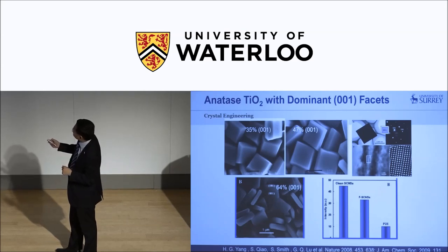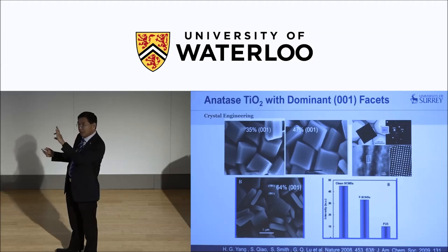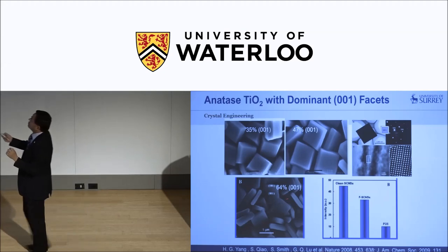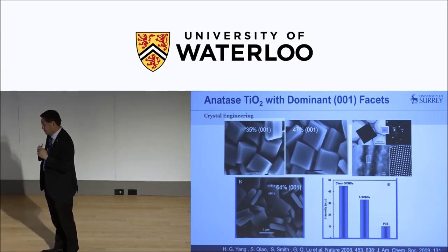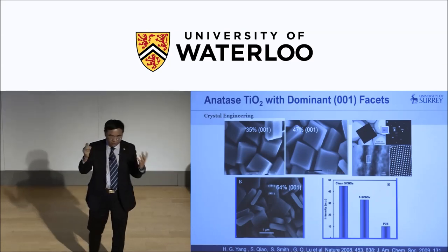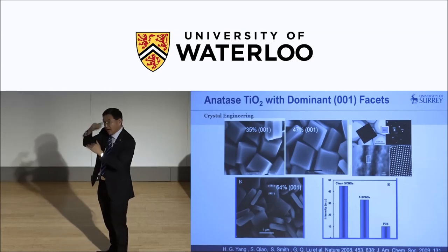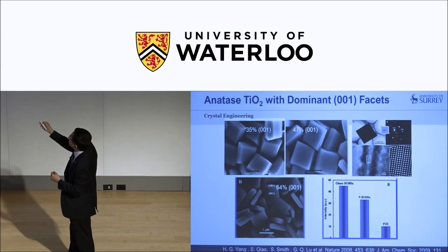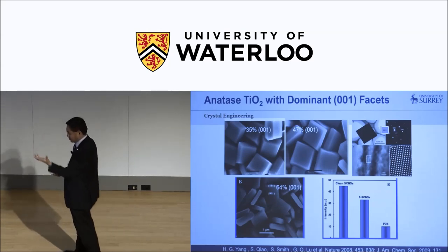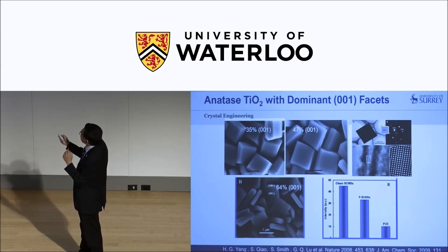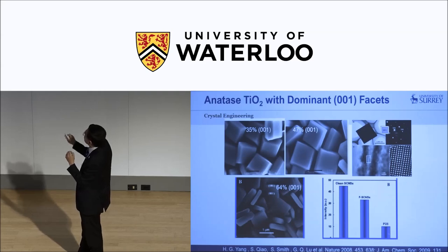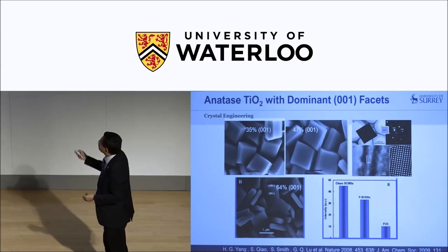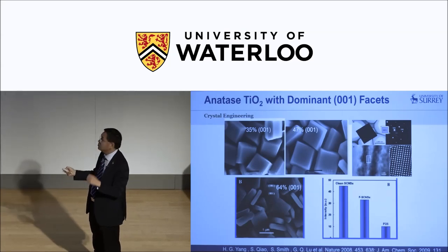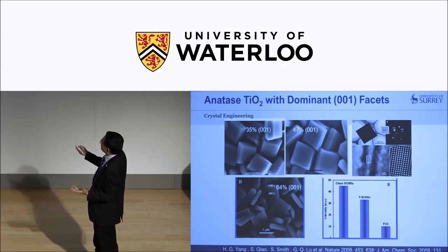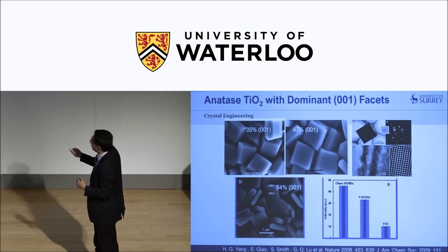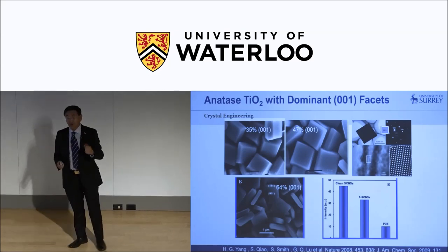And this is something we really did, and you can see that that's 64%, but later there was a JACS paper, another JACS paper, 2010, and we achieved nanocrystal. This is a microcrystal, single crystalline, and with predominantly the 001 facet. The isosceles truncated bipyramid phase, which has 8 faces, the size is sort of 40% or 36%. Now you can see that the reactivity probe testing in terms of the chemical, photochemical reactivity is quite clearly demonstrating. And P25, which is a gold standard you use in the labs, and the fluoride adsorbed and the clean single crystal titanium, you can see the difference in terms of the reactivity.